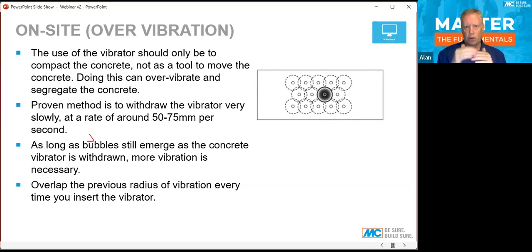So in this case, the grout comes to the surface, the aggregate goes to the bottom, and this can lead to cracking issues in a very weak top surface. So following the overlapping pattern that you see on the diagram there will help us, and waiting until there's no more air coming out and stop then, will help us to ensure that we have a well-compacted concrete.